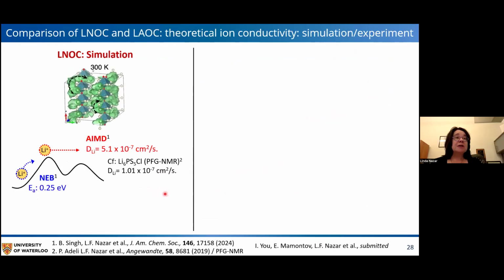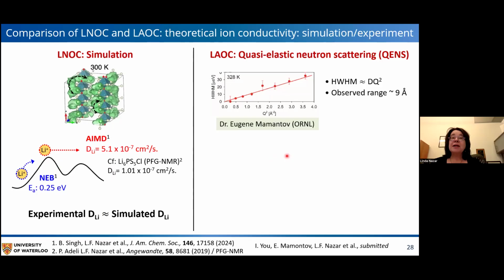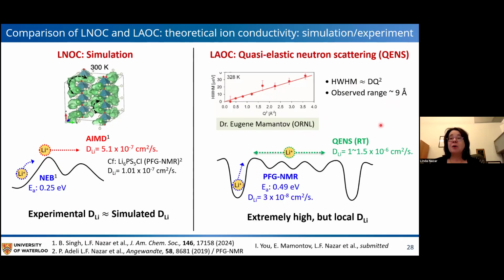So then, in summary, just comparing these longer chain oligomeric materials like LNOC, we have high diffusion coefficient, low activation energy, and long-range diffusion. Whereas in the case of the LAOC, we have done some QENS measurements together with Dr. Mamontov at ORNL. And these QENS, basically over a short range, because we're limited by the spectrometer, show that we have very fast short range diffusion in the order of 10 to the minus 6 centimeters squared per second.